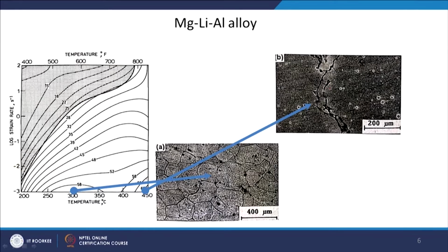The efficiency is around 60% here, whereas it is 58% here at lower temperature. So, with increase in temperature you have a new type of defects, and you can also see, if I am not wrong, that some cavities have formed here, maybe on the grain boundary, and you can also see this kind of cracking or cavities joining together, and you have a cavity coalescence kind of phenomenon.